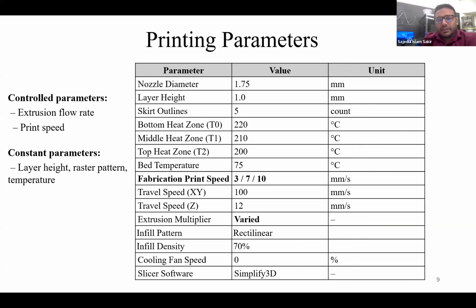So for the printing parameters we are using here, the nozzle diameter is 1.75. In the specification slide of the Gigabot X2, there are different kinds of nozzle diameter, like 0.4, and it is a big printer, so it has different diameters. For our lab, I'm using the 1.75 nozzle diameter, layer height 1 millimeter, and when we are printing, there is a skirt outline of five. And then the bottom heat temperature zone is 220 degrees Celsius, middle heat zone 210, top heat zone 200, and the bed temperature is 75.